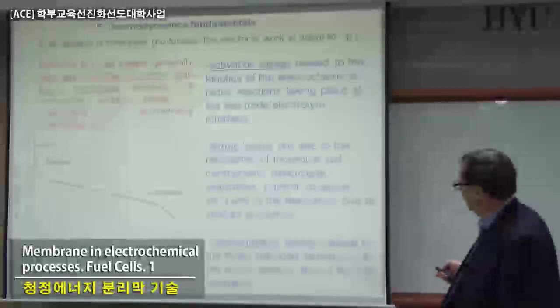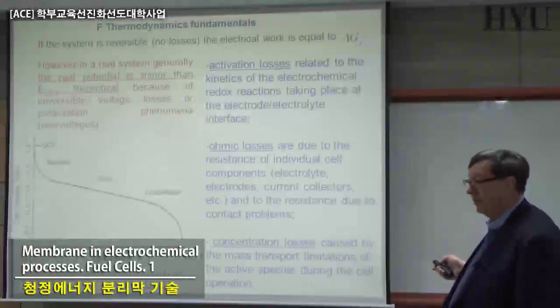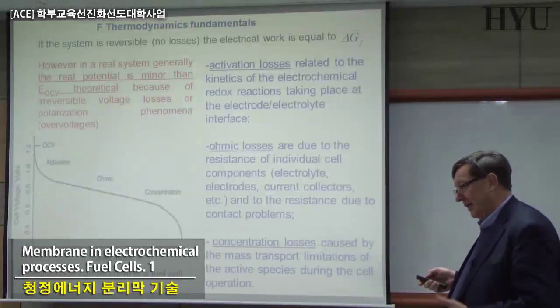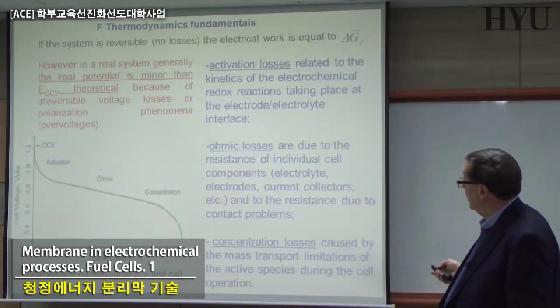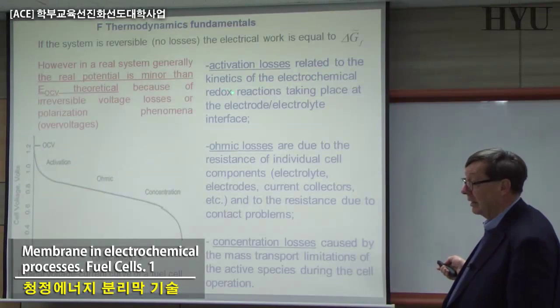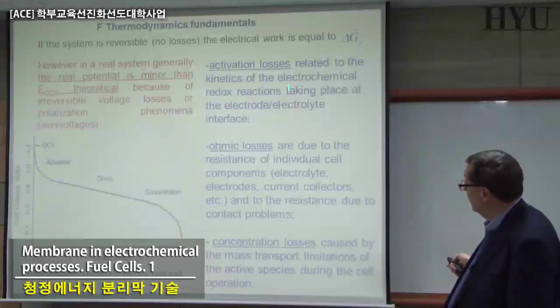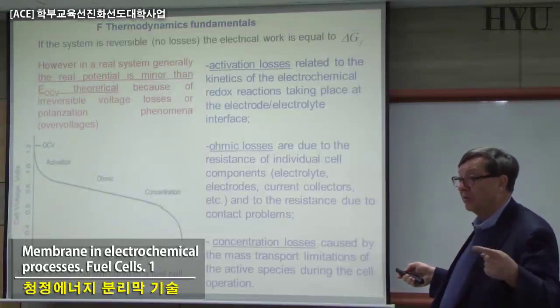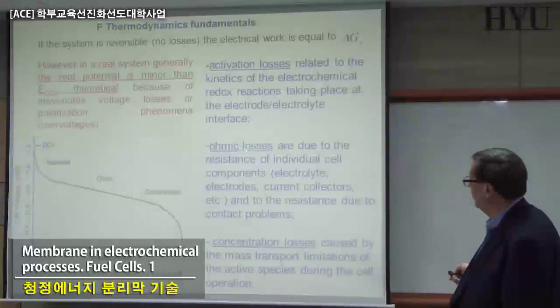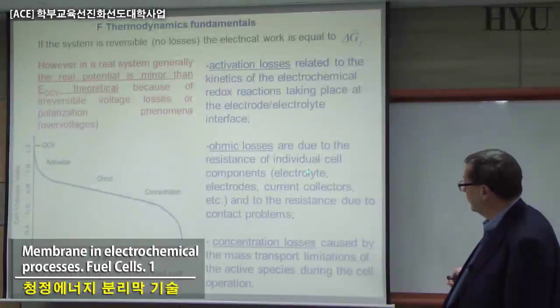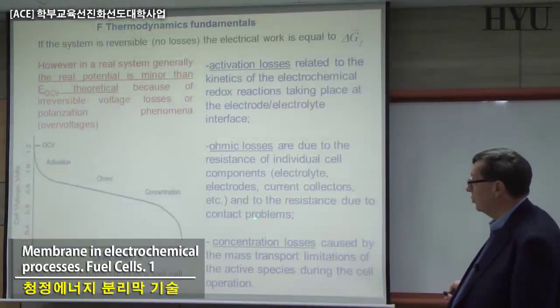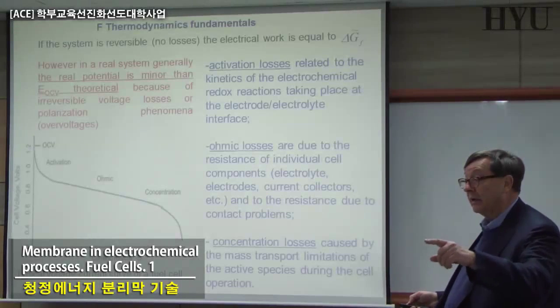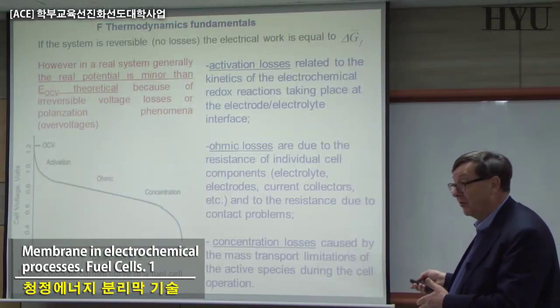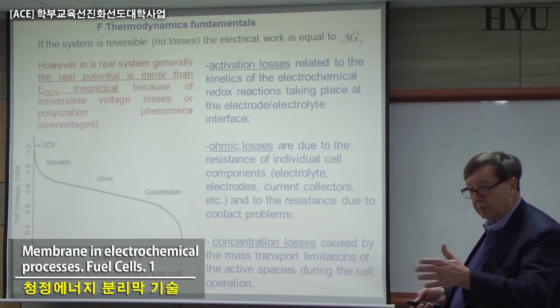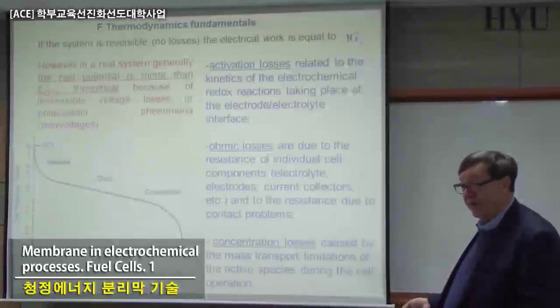The phenomena are exactly the same for all the membrane systems, and we call them activation losses. That means related to how the catalyst is working basically at the interface. The activation losses are related to the kinetics of the electrochemical redox. Catalysts are controlling the kinetics of your reaction, taking place at the electrode-electrolyte interface. So that is also called activation overpotential. The other ones are the ohmic losses, due to the resistance of the individual cell components, electrolytes, electrodes, current collector, etc., and to the resistance due to contact problems. Ions have to migrate from one side to the other and arrive at the interface, and any resistance to the transfer has an effect on the overall voltage.